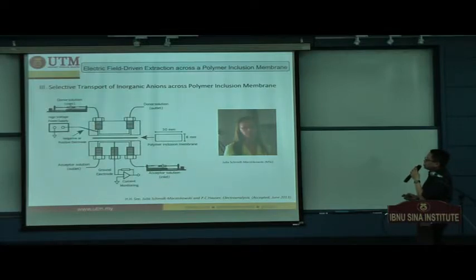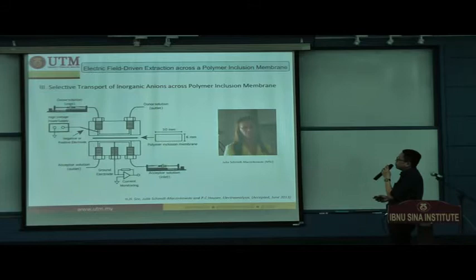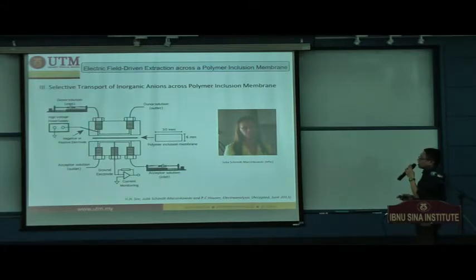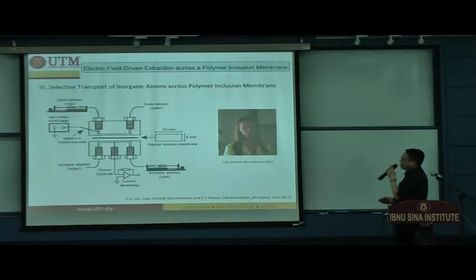So Yulia performed these experiments in a brand new extraction unit, which is much smaller compared to the previous one. And the sample is flowed in through a syringe pump into the very tiny extraction channel. And then on the receiving side, the receiving solution was flowed into the chamber by using a syringe pump as well. And the acceptor solution remains stagnant during the extraction, but the sample is continuously pumped through. The membrane size is much smaller right now, with only 30 × 6 millimeter. And after the extraction, the acceptor solution was injected directly into the capillary electrophoresis for quantification.